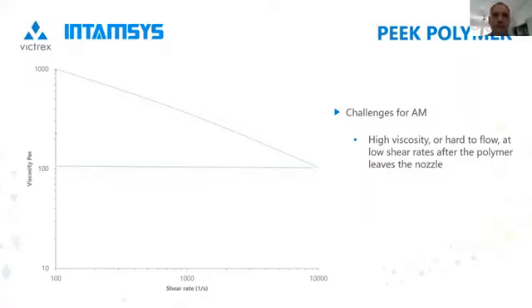Now, normally in other melt processes, work is put into the polymer in a screw or a pressurized system where the shear rate becomes high and then the material begins to flow more easily. But obviously for 3D printing, the material stays in a state that is more like the left-hand side of the graph, which is in a low shear state and hence higher viscosity as it comes out of the nozzle. And this high viscosity can cause sticking and disruption in a consistent flow.